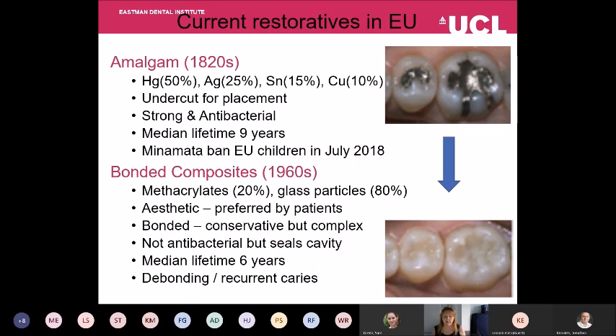The materials we've got for tooth restoration include, in the EU, the amalgams. These have been available for nearly 200 years. They consist largely of mercury, around about 50%, that's mixed with other metals: silver, tin, copper. What happens is you generate a paste, but in order to place this, you need to make an undercut in the tooth. The big advantage is that the materials are strong and they're antibacterial. And they've got a good lifetime of around 9 years.